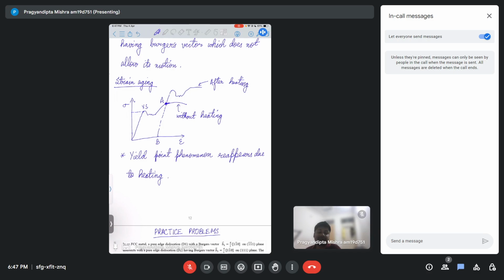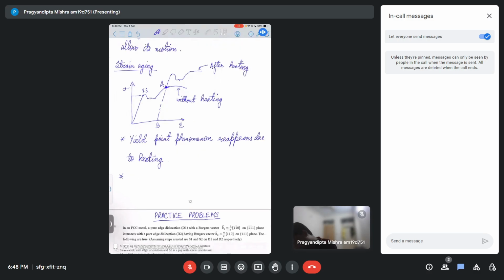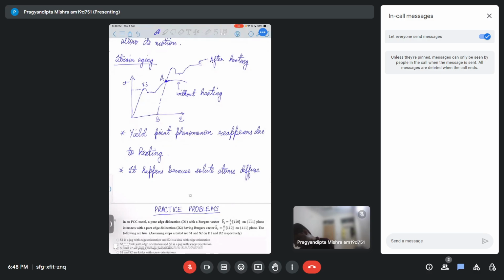Okay. So why does it happen? Because the solute atoms will diffuse to the dislocation location, and again they will not allow dislocation to move freely. Initially, when that yield point is reached, the dislocation is not able to move freely, right? But once we have moved beyond that, that atmosphere is broken down. So now solute atoms will again diffuse into those dislocation locations, and again it will not allow dislocations to move easily and yield to happen again. Okay. So essentially, when you heat it, solute atoms will diffuse to the dislocation core. Okay, so again you will have the reappearance of the yield phenomenon.